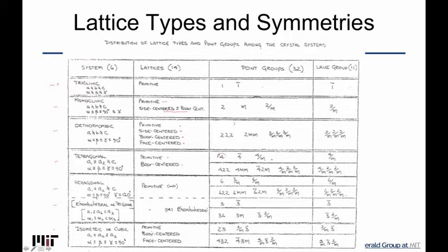and so on. Some of these are pretty obvious. If I'm going to choose a fourfold axis, then I better have a tetragonal, where the unique axis in tetragonal can be a fourfold. Sixfold fits into hexagonal, and so on. The cubic systems we already talked about with 2, 3, and 4, 3, 2 have the natural axial combinations that are compatible with thinking about the cube. The higher symmetries actually automatically fit in.